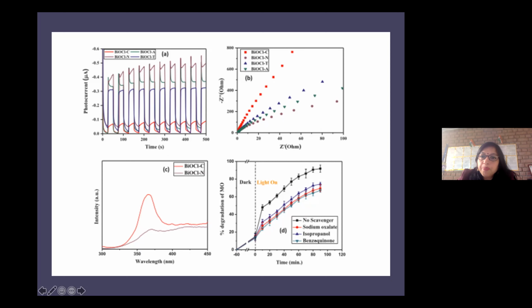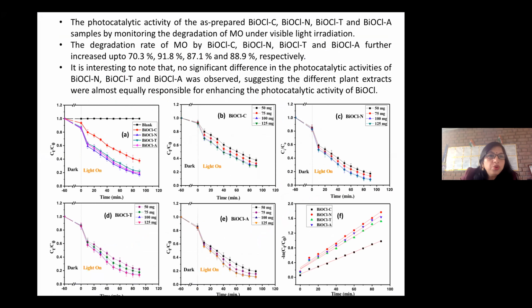And for checking which intermediate is responsible for the activity, we used sodium oxalate as the hole scavenger, isopropanol for the OH free radical scavenger, and benzoquinone for the superoxide free radical, because these free radicals and species are generated at that time and they are responsible for photocatalytic activity. And so we found that all the species are responsible for the process if we see the degradation of methyl orange. So here you can see the results of photocatalytic activity.